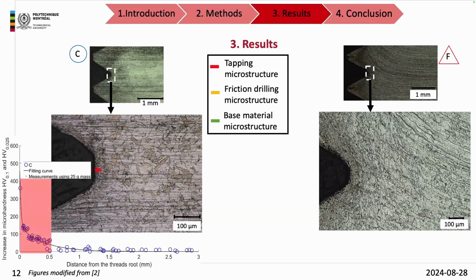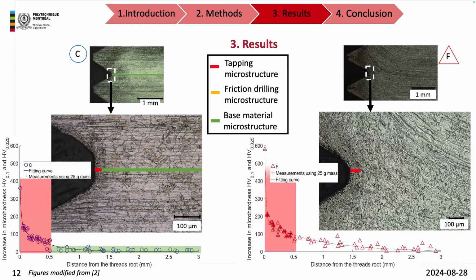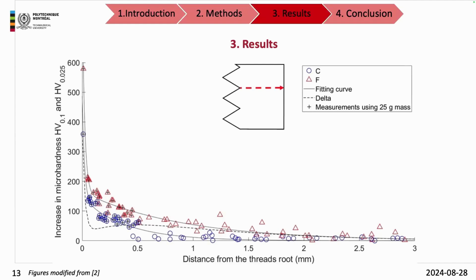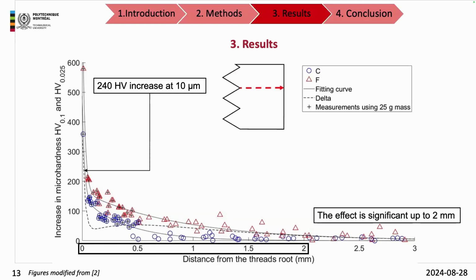If we now check if the grain and microstructure is in accordance with the hardness measurements, we note that for the conventional specimen, there is a hardness increase for the first 0.5 millimeters, and then we finally find the base hardness of the material. However, for the second process, we found a hardness increase also for the first 0.5 millimeters, but after we have also an increase in the hardness until 2 millimeters, and after those 2 millimeters, we found the base hardness of the metal. If we combine those results in the same plot, we note that using the flow forming process, hardness was increased by 240 Vickers at 10 micrometers from the hole surfaces, and we have a significant effect of the flow process up to 2 millimeters.